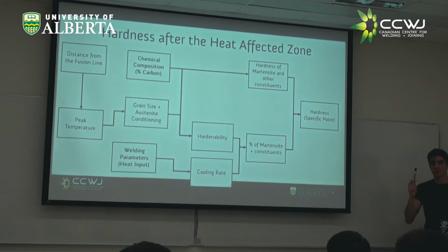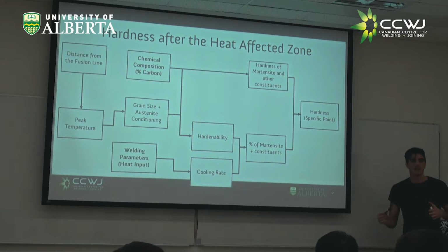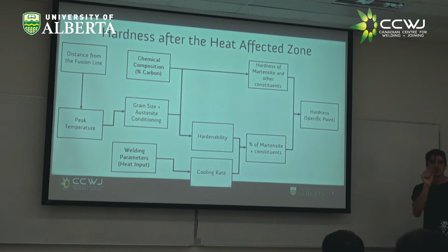We usually assume that all of our alloying elements are dissolved in our austenite, except for some really stable carbides like niobium carbides or vanadium or titanium nitrides, which don't dissolve. That's true, but we are going to see that those kinds of elements play a little role in the predictions. But the chemical composition of your austenite is one of the most important things.